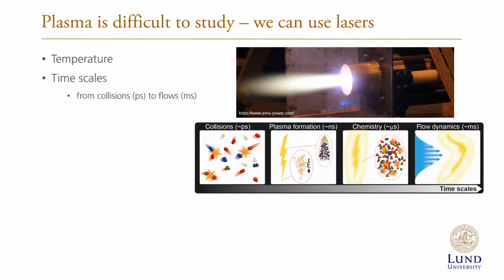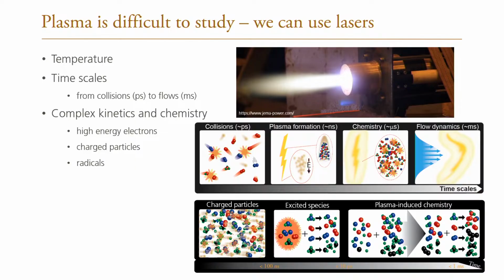because lasers can be pulsed. You can go down to picosecond level to really understand the dynamics between the electrons and the particles. You can follow very complex chemistry because we can follow this in both time and space. So we can study the high energetic electrons, and we can do that simultaneously as we study charged particles and radicals that are only short-lived and there for a very short amount of time. We can't do this with anything else.